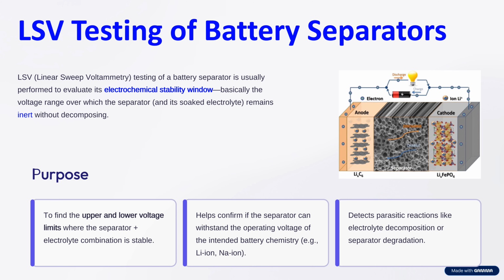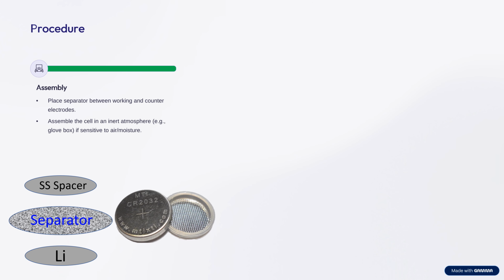So first is how to make this testing. Place a separator between working electrode and counter electrode. For the working electrode, you can use stainless steel. There should be no active material because you are going to evaluate the separator. And for the counter electrode, you should use lithium foil, sodium foil, or magnesium foil for magnesium ion batteries. First, you have to place the lithium foil inside the negative casing, then put the separator, then place the electrolyte, and then put the stainless steel spacer without any active material and close the positive casing.